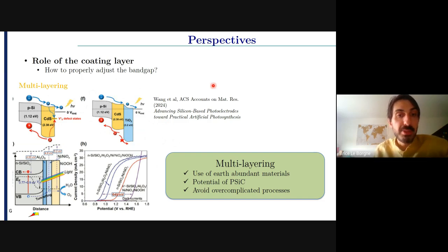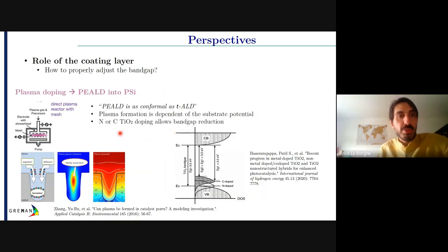So you need to find a good balance, but it's a possibility, definitely, and you can find other ways to tune it. But the method we are working on now, since we are working on ultra thin layers, is to try to do a plasma doping, so to directly in situ dope our ALD layer thanks to a plasma. So you can do nitrogen plasma, for instance, and you dope it. The literature showed that with nitrogen doping, you can reduce the titanium dioxide band gap.